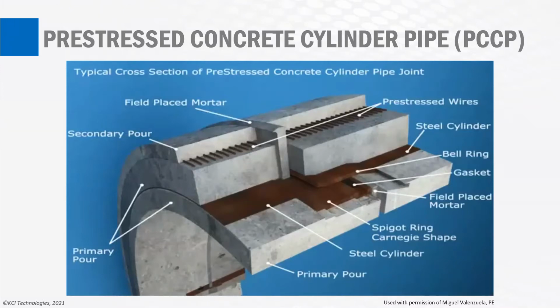The steel cylinders used in PCCP are first hydro-tested, just like with steel pipe, after which joint rings are welded to the cylinders. In embedded PCCP, the steel cylinder, as shown in this cross-section, is cast within a concrete core. After curing, hard-drawn steel wire is helically wrapped around the exterior of the cylinder. This results in producing a predetermined compression of the concrete and steel core. The wire is then covered with cement slurry and dense mortar coating for corrosion protection.